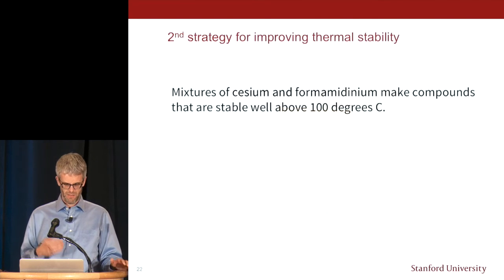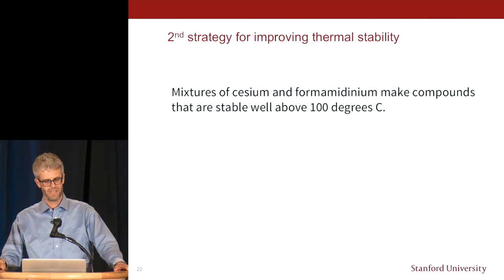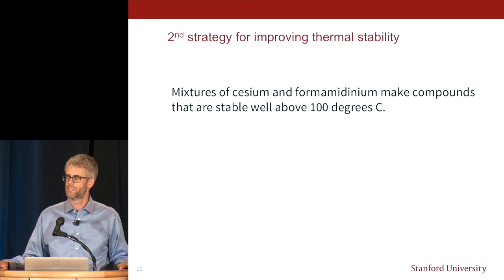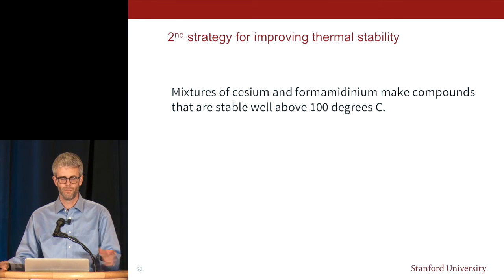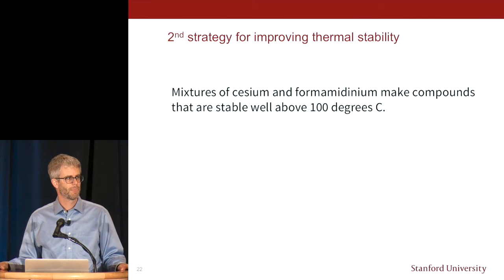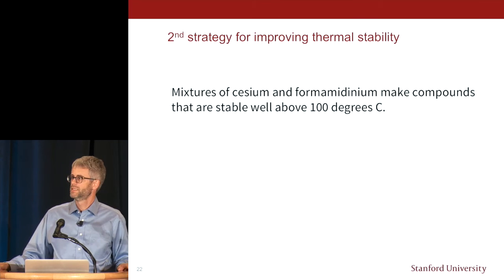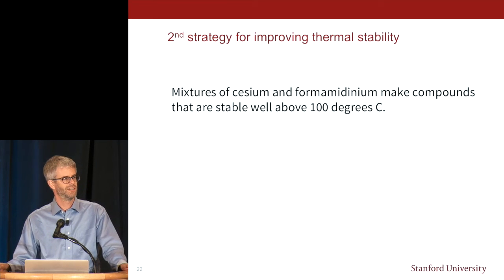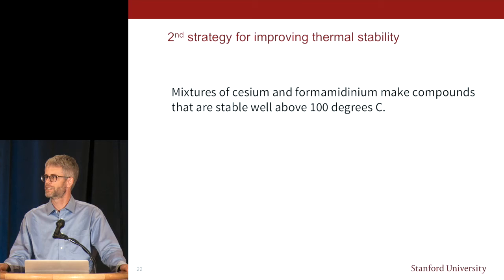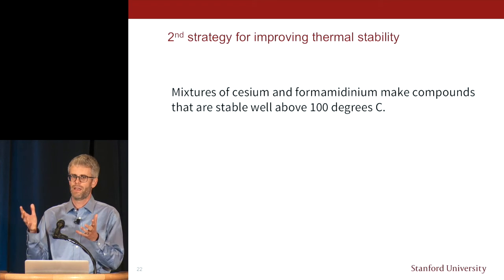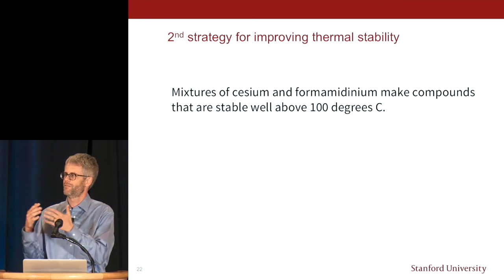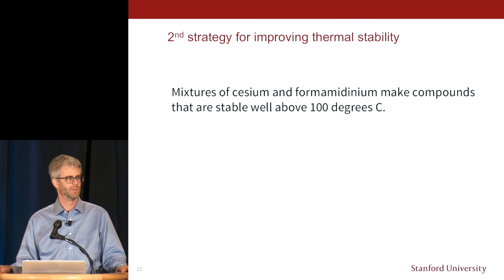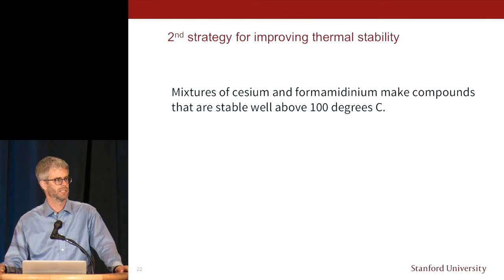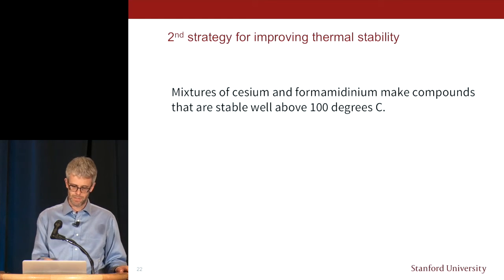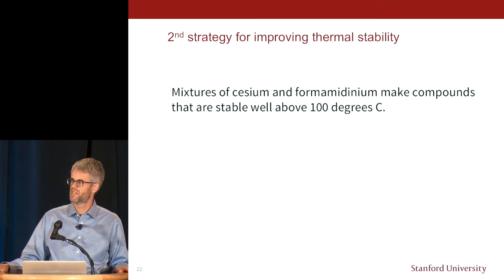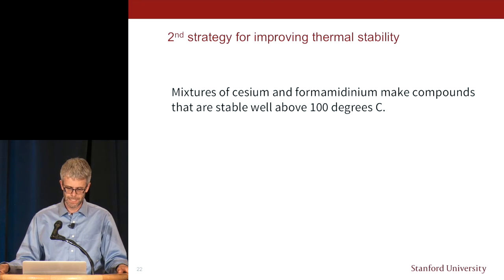But you want to have multiple layers of defense, and it's also best to just replace the methyl ammonium with cesium and formamidinium. Why do we use both? Cesium is too small to fit in the lattice, formamidinium is too large, and if you mix them, then on average they're the right size, and it gives you a more robust crystal structure. And that just gives us the temperature stability that we need.